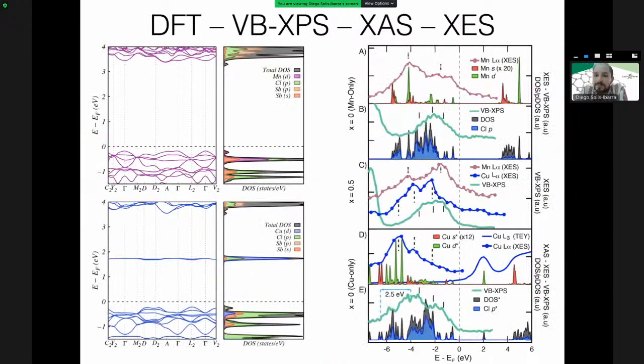And what we did then was we wanted to understand these materials and understand their electronic structure. So we rely on DFT calculations, and we validate those calculations with extensive studies with XPS, X-ray absorption, and X-ray emission, which told us that we really had done a good job modeling these materials and that we really understand how to model these materials.